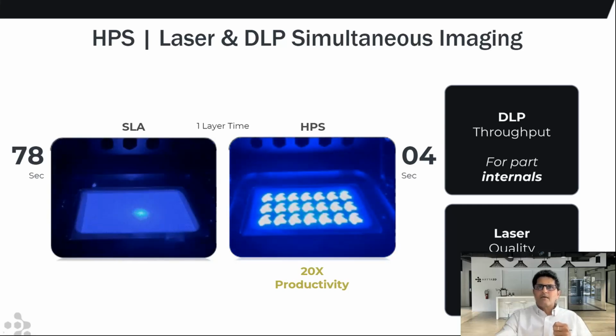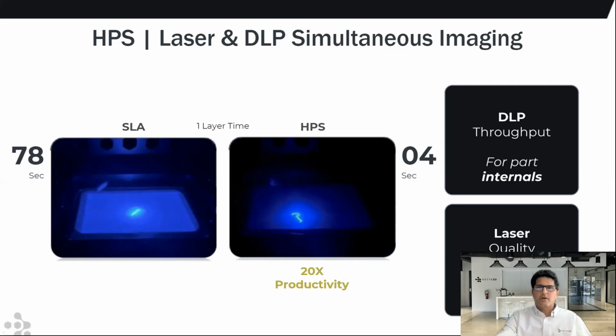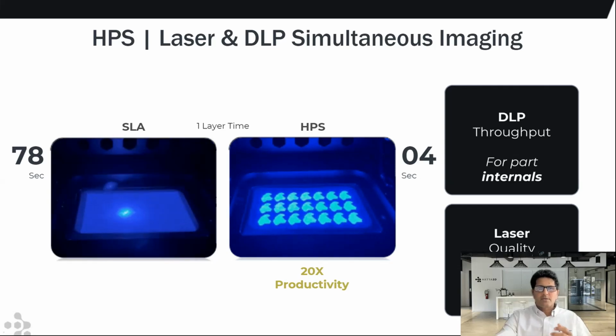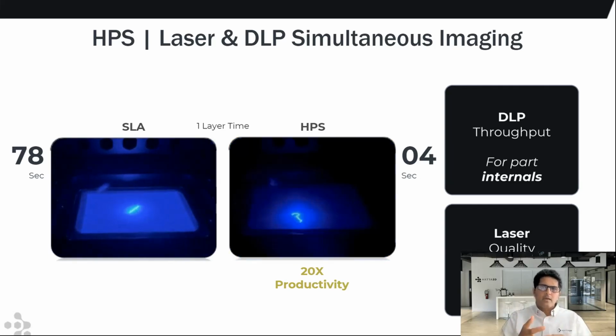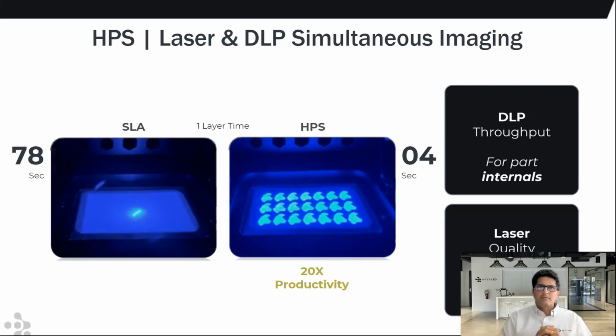And here's the result. A layer that takes 78 seconds on an SLA generally takes about 4 seconds with our technology on the HPS. And so it's anywhere between a 10 to 20x productivity based on geometry, size, number of parts on a layer. But typically we are seeing about the same SLA quality part being built with HPS about 10 to 20 times faster without any initial wet fill and without any recoating required. And that truly increases the value and the advantage that you get out of the system. And tying it back, it's essentially getting an SLA quality part at DLP speed without the disadvantages of conventional laser-based SLA.